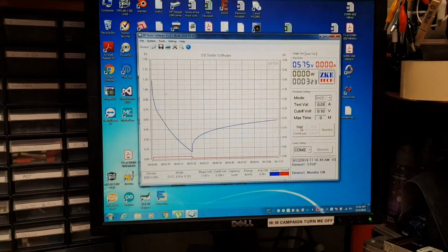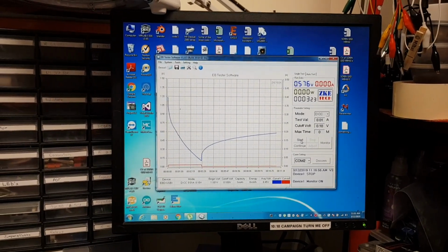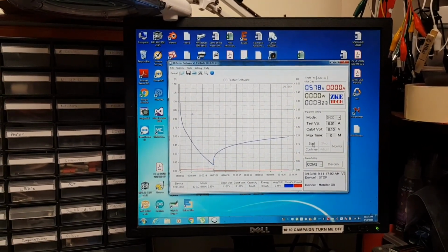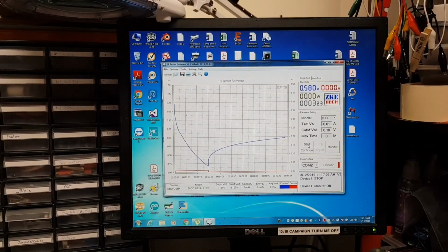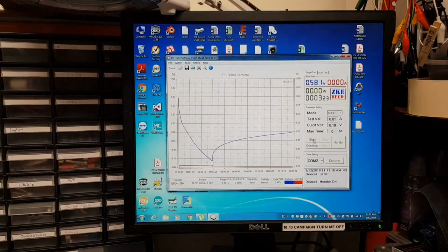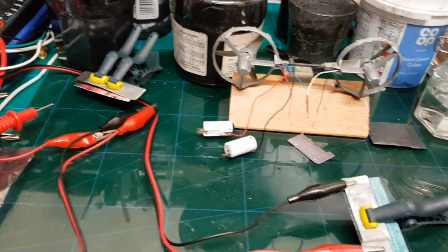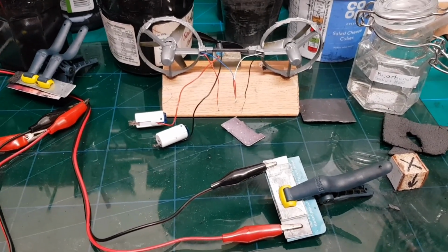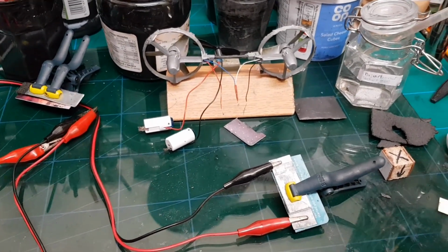But this test was exactly as I made it. I haven't charged it. And this is exactly what we are going to do now. We are going to run a few charging, discharging cycles to see if we are improving this non-performance. So 3 minutes and 23 seconds at 10 milliamps. Yeah, I was hoping much more from this. I repeat, it has 0.2 grams of active material. I'll be back.